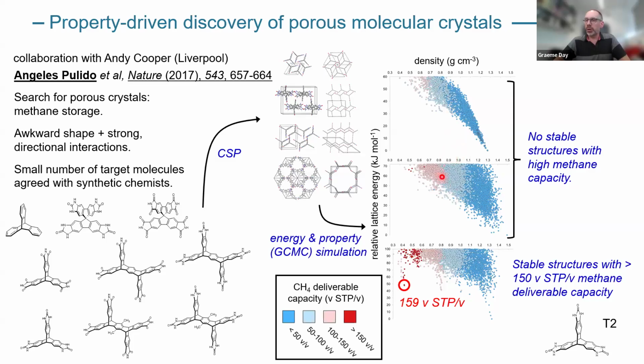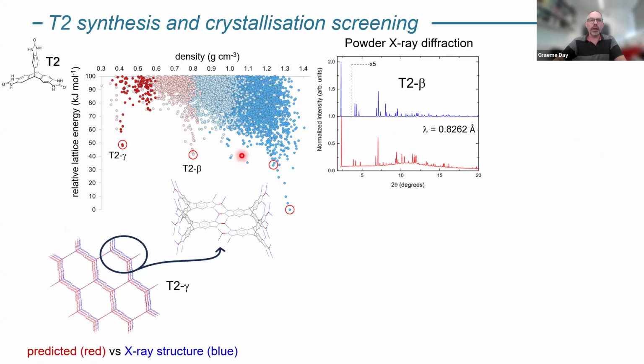These two landscapes at the top, they don't. So immediately we know that it's not worthwhile making those molecules, whereas this one on the bottom has some predicted structures which do have the properties in the range that we want. This molecule here, which corresponds to this one here, which we call T2, is a molecule that then got made in the lab. And then after some crystallization screening, I'm circling here these structures from our predicted landscape that get found in the lab.